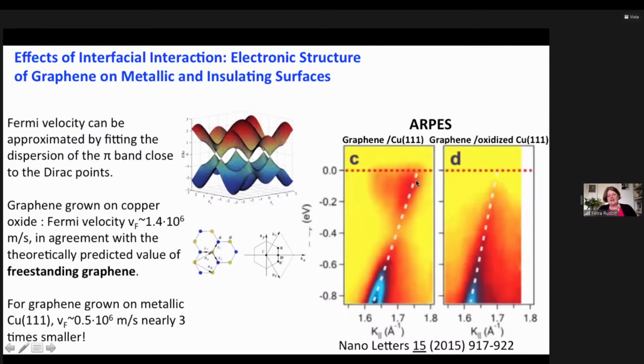Well, actually, this is the valence band photoemission of graphene on the pure copper. And you see the Dirac cone here. You only see part of it, but it is below the Fermi level. So with photoemission, you can only see states which are occupied. And you see that the point where the two curves cross is below the Fermi level. So on pure copper, there's actually a transfer of charge from the copper to the graphene.